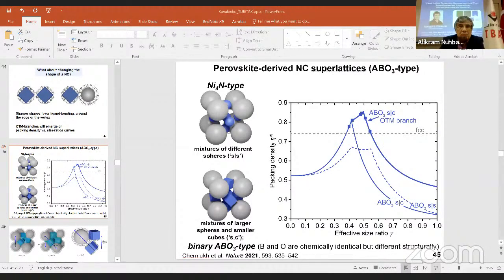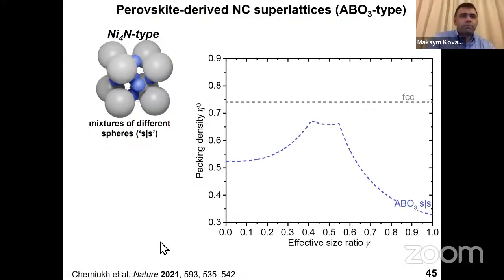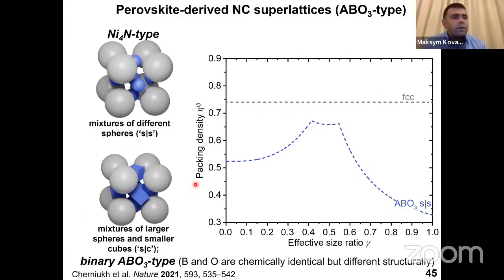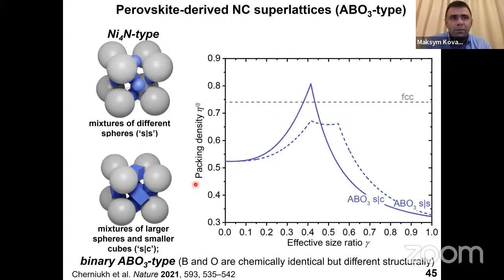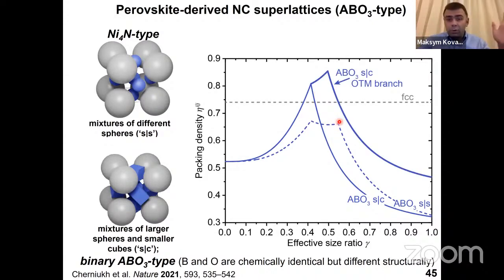So, all right. And so, if you compute the packing density at any size ratio, this lattice is indeed unstable. But now when you mix a cube and a sphere, you do get the perovskite type lattice, because already without any assumption of ligand deformation, at least in some narrow size ratio, it will have very high density. But if you assume in addition the ligand deformation, you will expect an even broader range of stability.